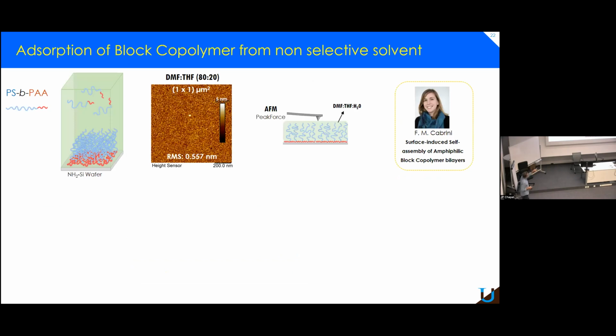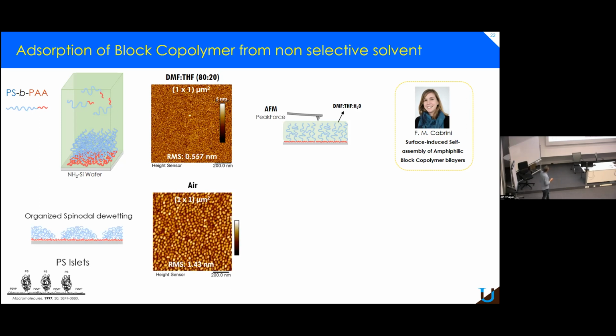Actually, at the beginning, I talked to you about Flavia, who was working on other topics, block copolymer adsorption. If we make a bilayer, if we adsorb a block copolymer to make a brush, not a dense brush, on a wafer substrate, and if we measure by AFM in an organic solvent, the surface is smooth and nice as expected. If you remove the solvent, what you see is something that I call an organized spinodal dewetting, something that was already seen many, many years ago. So you have a bumpy structure. And this bumpy structure is polystyrene, okay?